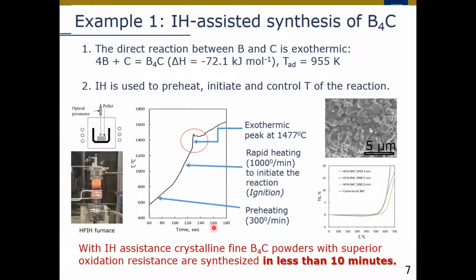It's in seconds. So we preheat our mixture and then ignite with a very fast heating rate higher than 1000 degrees per minute and initiate the reaction. And then we post-heat to control properties of the product. As a result, we get powders with particle size of a few nanometers, and our powders demonstrated exceptional oxidation resistance. So we can conclude that with induction heating assistance, we can synthesize boron carbide in less than 10 minutes.